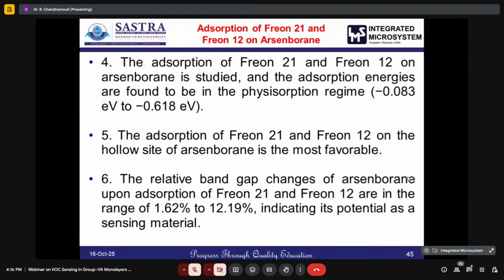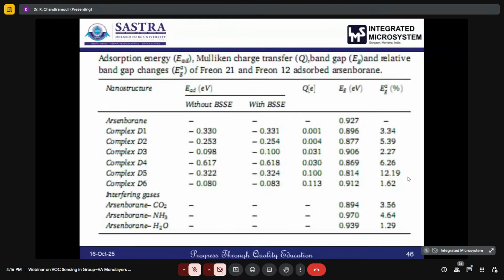And here in the CFC, chlorofluorocarbon, we used two target vapors, that is Freon 21 and Freon 12. The adsorption energy is found to be in the physisorption regime, and the adsorption of Freon 21 and Freon 12 on the hollow site is found to be more favorable. Relative band gap changes are also calculated: for Freon 21 and Freon 12 it is 1.62% and 12.19%, indicating a good sensing material. These are the adsorption energy, charge transfer, energy gap, and relative energy gap variation, reported with and without the basis set superposition error.